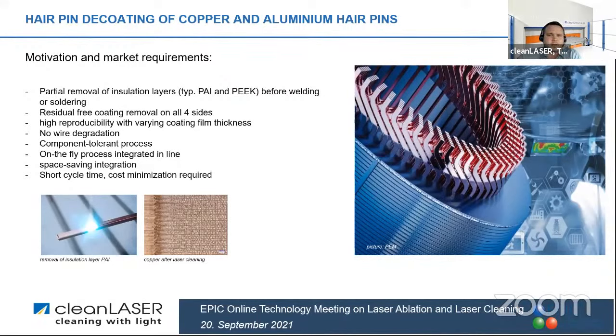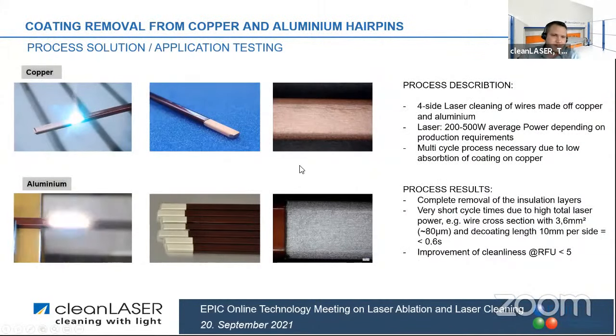And exactly here, this is a challenge for laser because you have to treat the wire completely around, meaning from all four sides. And you also have the requirement from the market that there is no damage to the material itself or degradation, and that the process runs very fast, on the fly, inline in this complete manufacturing machine. This is challenging because we always have to find out the right parameter setup, because the coatings are very different. What I have written here on this slide is an example for coated copper and aluminium.